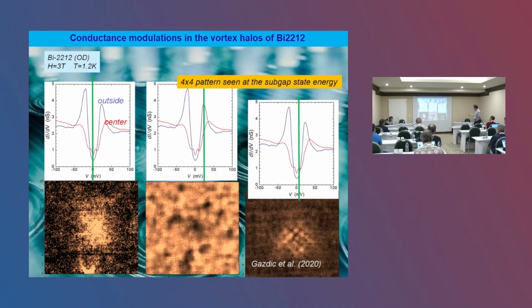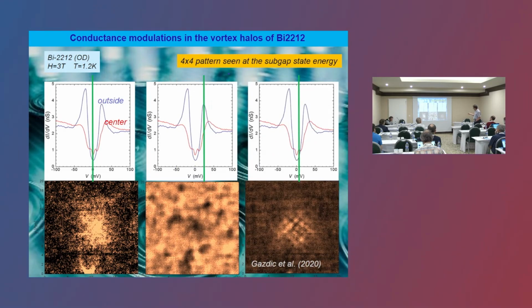But interestingly, if you plot the conductance map at the position of these subgap states, the ones which are seen at the center of the core, you reproduce the conductance modulation which were associated with some QPI or charge density wave. So there is an indication that this subgap state, at least in BSCCO, we see no modulation in YBCO, that the subgap states are more or less linked to the conductance modulation which are seen in the vortex cores.